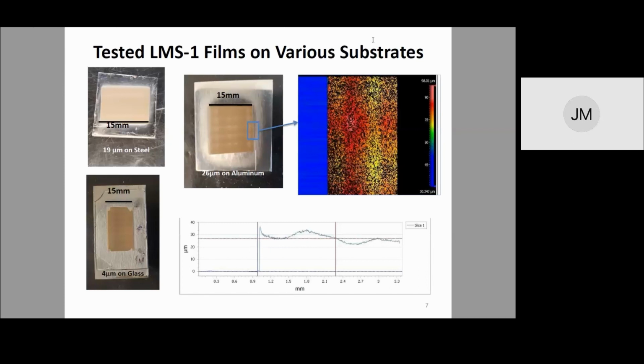Right of that image is a picture from our Zygo surface profilometer showing the step height of the film compared to the substrate being the blue on the left, and then the red and yellow itself is the film. The line plot corresponds to that surface profilometer image, showing that the average thickness of the film throughout was about 26 microns. Next slide, please.